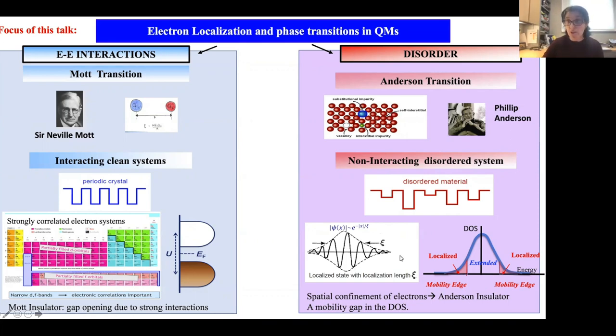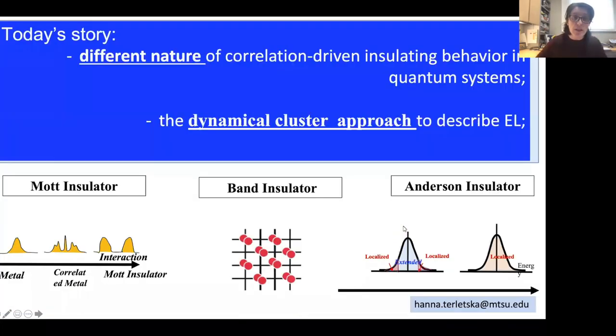Unlike Mott localization, Anderson localization is not characterized by a gap opening in the density of states. It's characterized by a mobility gap opening in the density of states. So there is an energy level which separates localized and extended states. And as you introduce more disorder into the system, this mobility edge will cross the Fermi level, and the system will become an Anderson insulator. So in today's story, I would like to show you that electron correlations, due to the different nature of the electron-electron interaction and due to disorder, can lead to different natures of insulating behavior in materials. This can be Mott insulating, band insulating, or Anderson insulating. And I will demonstrate how the dynamical cluster approximation can successfully describe these different scenarios of electron localization.